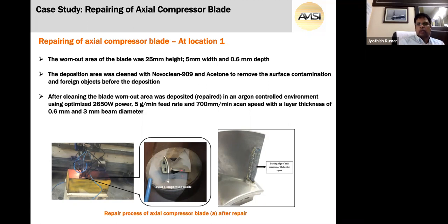So we used NovaClean 909 and acetone to remove foreign objects such as oil, dents, and any other dust deposited on the surface before the deposition. After cleaning, we took it into a controlled argon chamber, because it's very important to have a controlled argon chamber in the LMD process, to avoid oxidation.